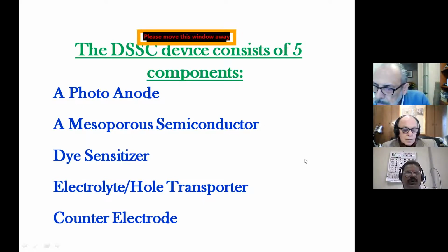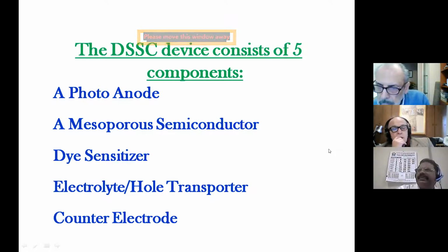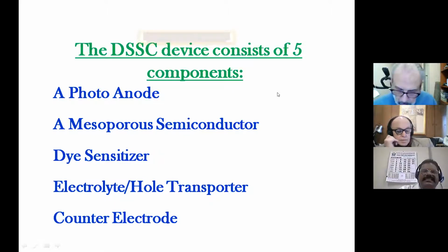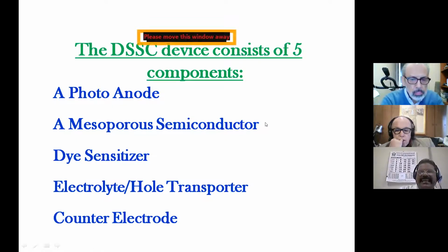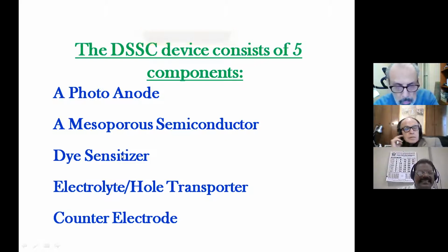This is having basic 5 components. Very important, within a few rupees, within 1 rupee, we can fabricate this solar cell. That is the peculiarity in making these dye-sensitized solar cells. There are 5 components involved. One is the photoanode, another is the mesoporous semiconductor. Here, titanium oxide, TiO2, is used. Then we use the dye sensitizer, a natural dye. More than 50 types of naturally available Indian plant extractions are used as dye sensitizers. Here, the electron-hole transporting material is iodine. Here, the counter electrode is platinum.